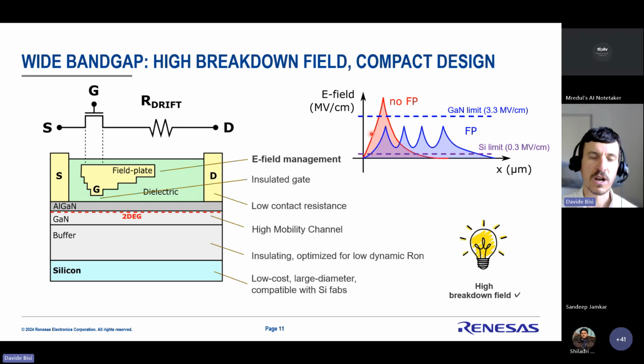And so you can see here, in this instance, the gate is isolated with the dielectric, and also you can see the field plate structure, which is used to basically spread the electric field across the gate to drain distance. And so we can get a better engineering, a better spreading of the field through the device without any peaks that could damage the device prematurely.